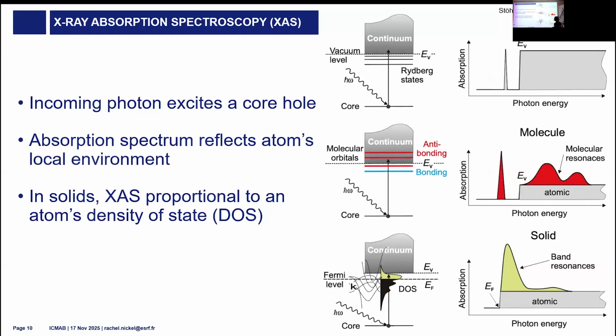In a standard X-ray absorption experiment, we produce a core hole, and then either the absorption of this core hole is measured directly through a transmission measurement, or we measure either Auger electrons or fluorescence that's produced in the decay process. We get information about the local environment of the atoms. So you can see there's a difference if we're talking about just an atom, one that's bound in a molecule, or what we often measure at ID32, which is solids. And the resulting spectra tends to be proportional to the density of states.